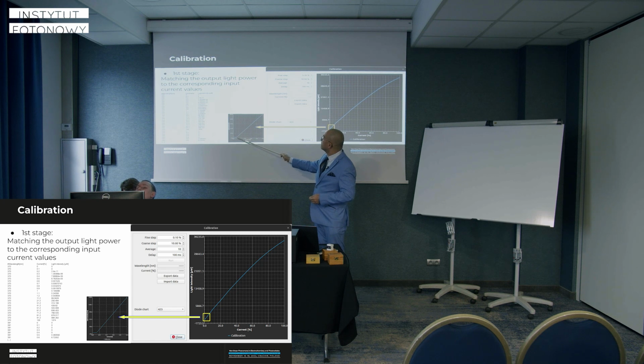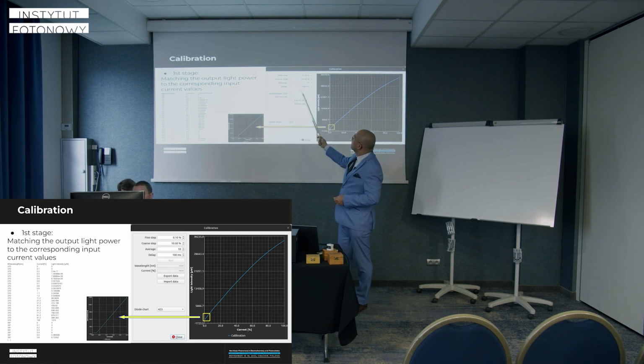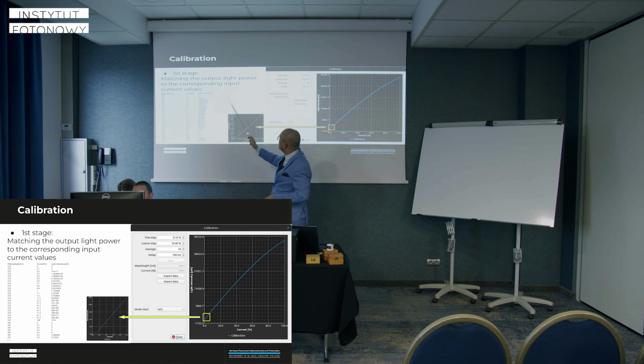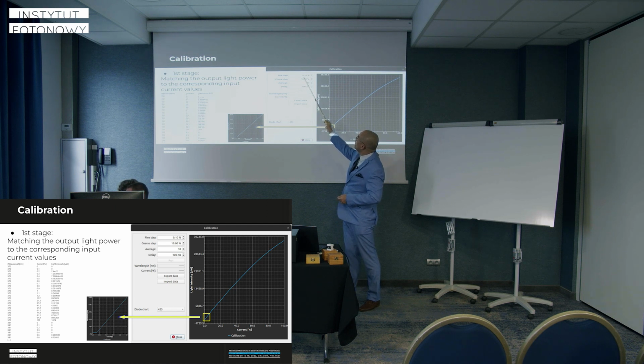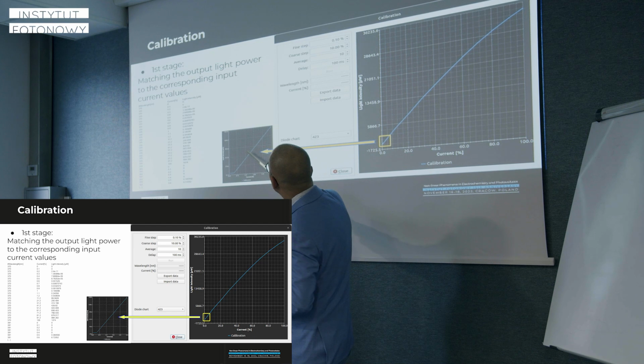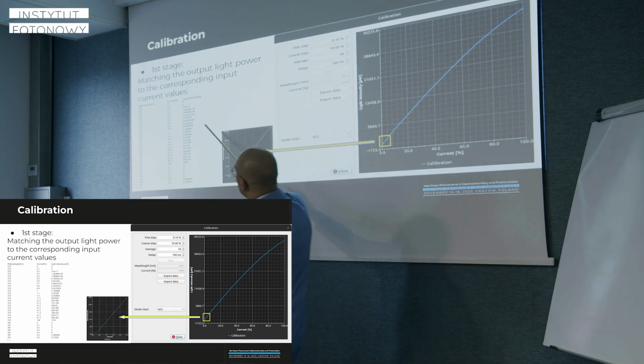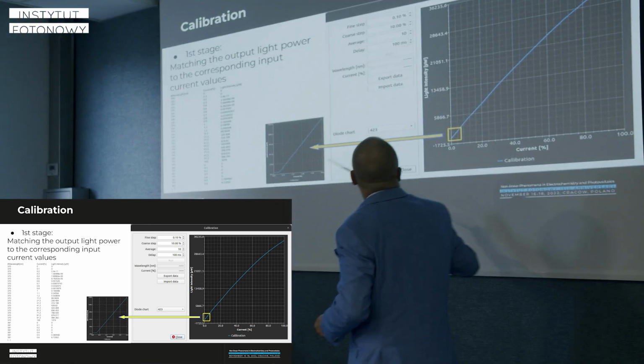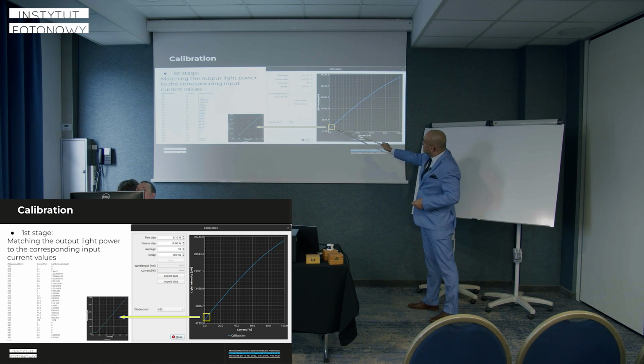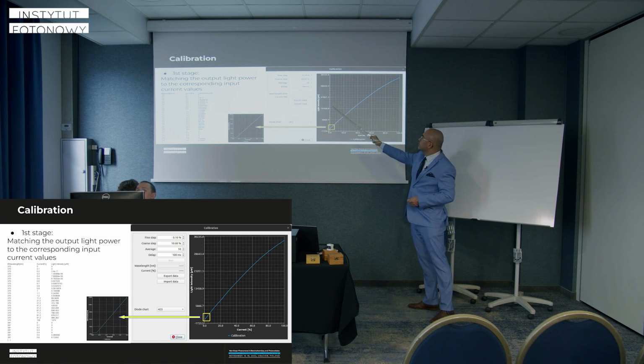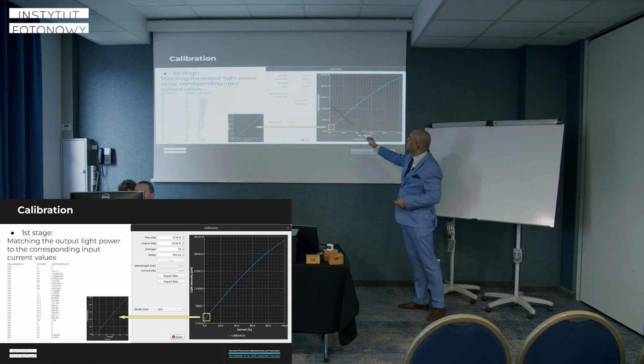It picks up at a few percent, and the calibration is done this way: from 0 to about 1%, we increase the current with a step of 0.1%, and when it reaches about 1% of its whole current range, then we increase with 10%. So we can see that there are some very small values, and after that it increases, not necessarily linearly, so this is a nonlinear characteristic, so that's why we have to know how much current we have to power the circuit with to obtain such a power in milli or microwatts.